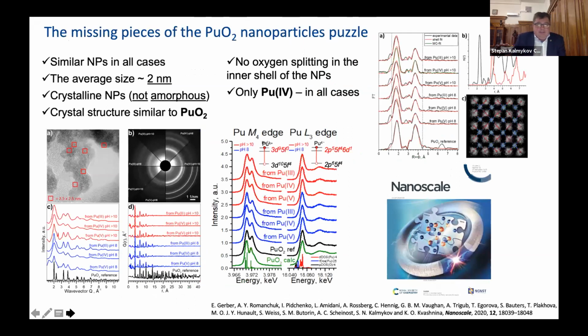So this is a small conclusion concerning this part of the work. Again, we have nanoparticles of 2 nanometer size. They are not amorphous. They are crystalline, which we can see definitely from TEM, X-ray diffraction and selected area electron diffraction. The crystal structure is similar to plutonium O2, and we have no oxygen splitting in the inner shell of the plutonium nanoparticles. And this is only plutonium-4 in all cases, with plutonium-3, plutonium-4, and plutonium-5 taken as precursors for preparation of these nanoparticles.